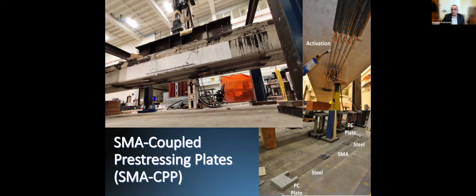Basically, the idea is very simple. We have here 2 plates. They are not connected, but they are coupled with the SMA reinforcement that's running in between them. And these are precast plates. We can also supplement the reinforcement with some steel just to cut down on the cost of the SMA material. You simply attach these plates to the soffit, in this case of a PPC deck beam. Essentially, it's a box beam with some cracks in it, and we wanted to repair and strengthen it. So here we used epoxy with some anchorage applied as well.